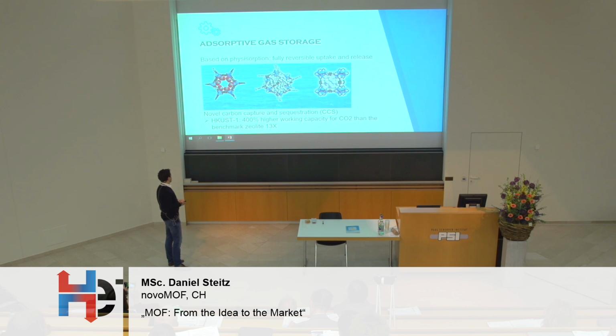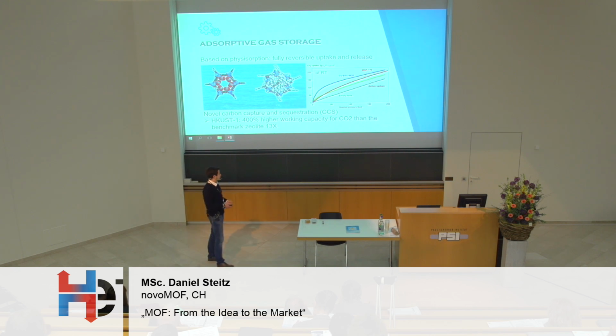So, for example, here's one study where they could prove that one of the MOFs, which is called HKUST-1, actually showed 400% higher working capacity for CO2 than the benchmark zeolite 13X. And going to methane, there was a possibility to show that when you use an empty tank, which is the gray line, and you put methane in it, you get this curve. Then you have the green one, which is active carbon. And then compared to the other ones, the red and the blue curve, you see that there's a significant benefit when using MOFs within a methane tank.